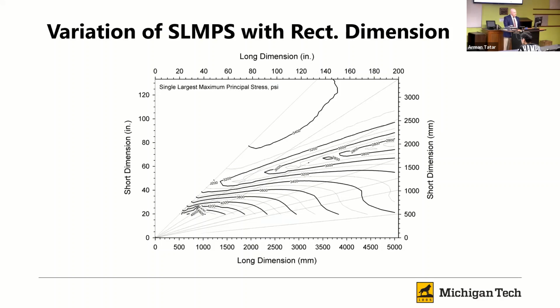And what we find is that there's quite a bit of difference in the single largest maximum principal stress depending on area and aspect ratio. So out here, we're saying that glass would have only had about a 2800 PSI stress in it. Whereas if I go to other areas, say something very small or something very square, then that number gets quite a bit larger. Okay, and this has to do with the way the stresses are distributed across the plate when it's loaded. It has to do with the aspect ratio and the area with respect to its thickness.